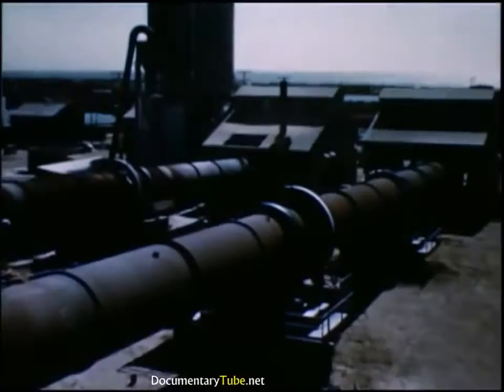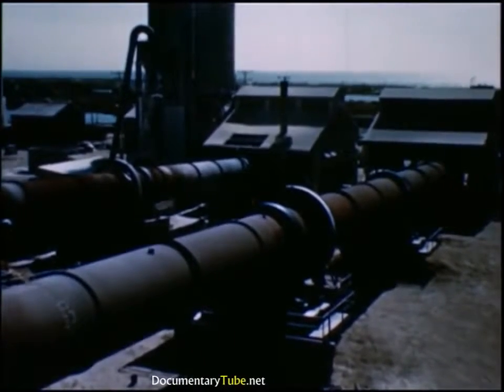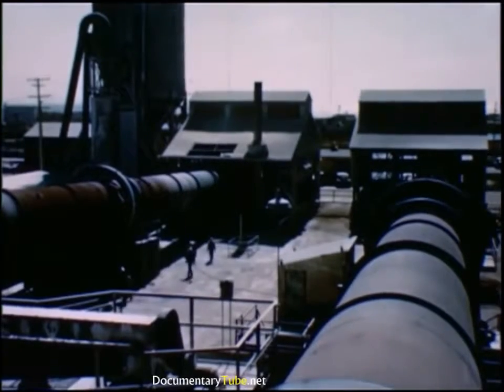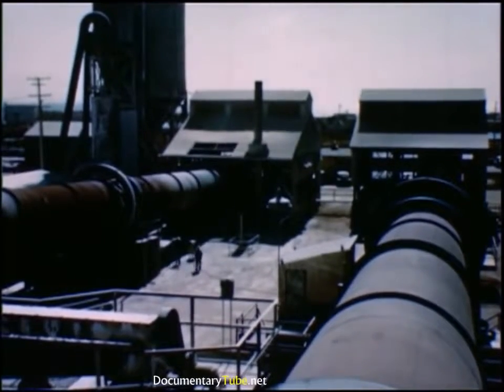The thickened magnesia from the last tank is concentrated by Oliver vacuum filters. A large drum revolving in a slurry tank draws the suspension onto a filter cloth that removes the water. The cake dries partially as the drum carries it to the scraper, where it is removed from the filter by a wire. This milk of magnesia is almost of pharmaceutical purity without further refining. The cake falls from the drum into a screw conveyor which feeds it into one of these giant kilns. The milk of magnesia is calcined just as the starting mineral was, except that water is given off in place of carbon dioxide.